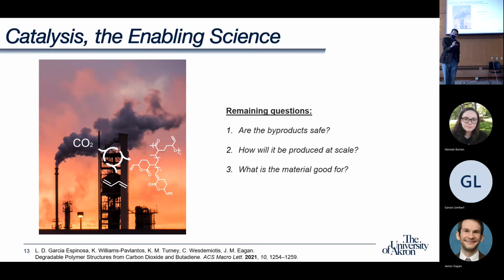In theory, if a carbon dioxide molecule came in, you would get a moiety known as an ester, and you would have a polyester. And polyesters hydrolyze very readily in the environment. They are the compostable plastics that we like. So it's a simple idea, let's get CO2 into there. But from the chemistry perspective, that is enthalpically and entropically very disfavored.